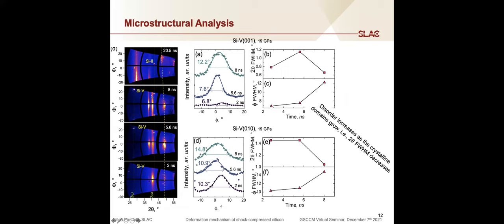The development of textures, of mosaicity and defects, is something that happens at a second moment. So it really seems that the moment at which the system relaxes from the uniaxial compression corresponds to the phase transition rather than a classic plastic deformation. I'm sorry, I hope this was clear.